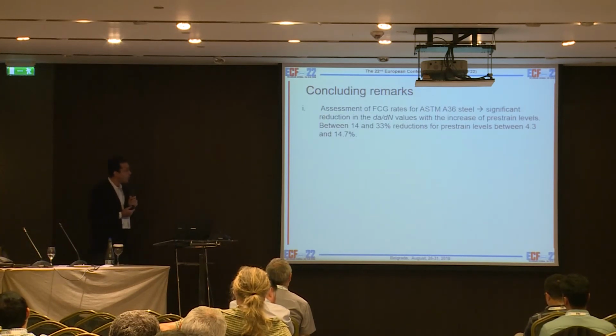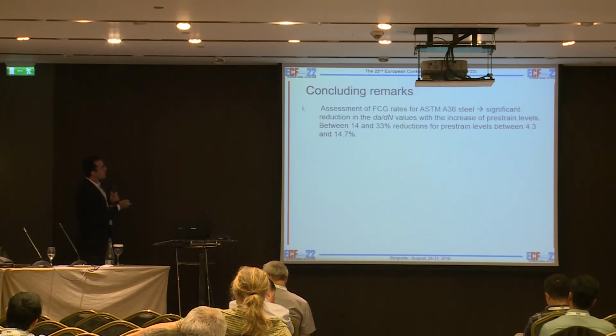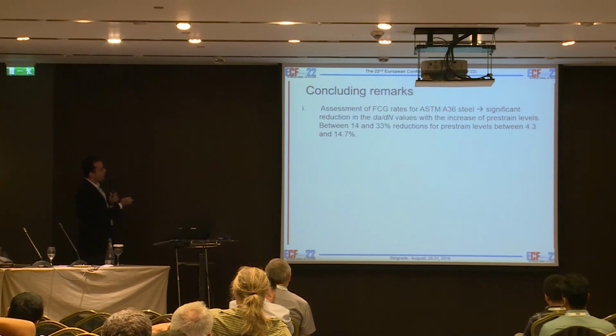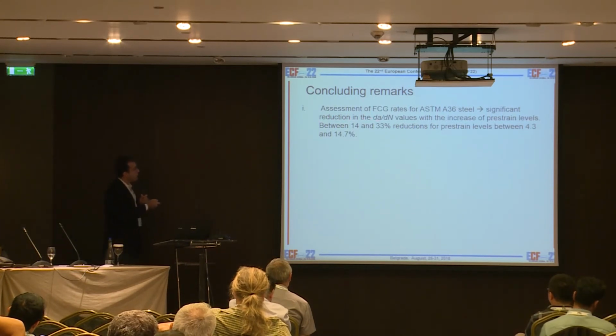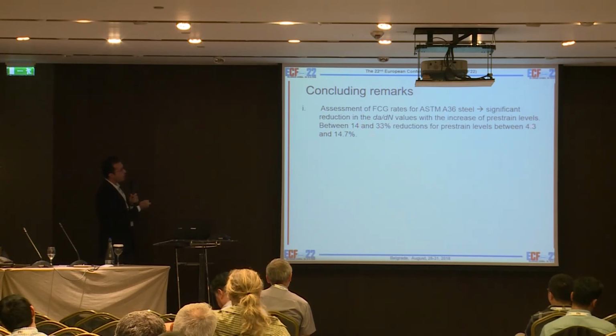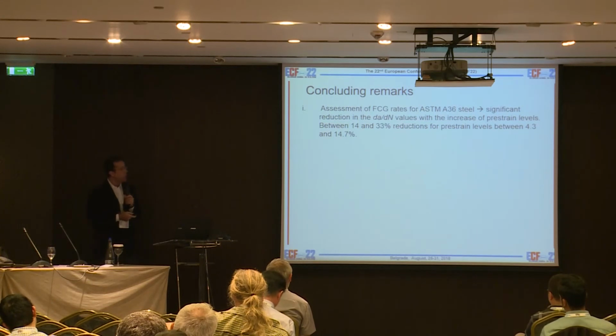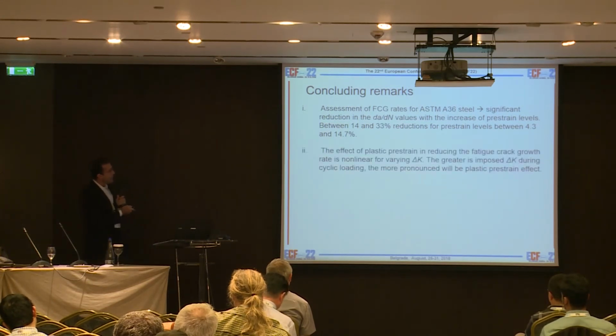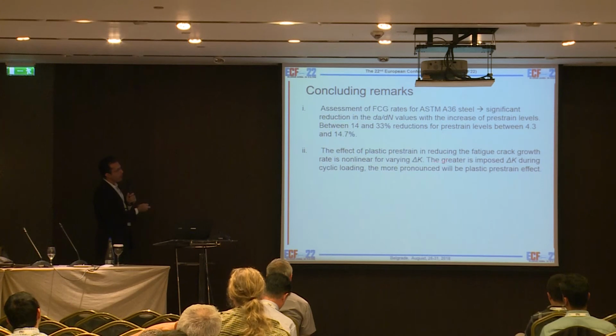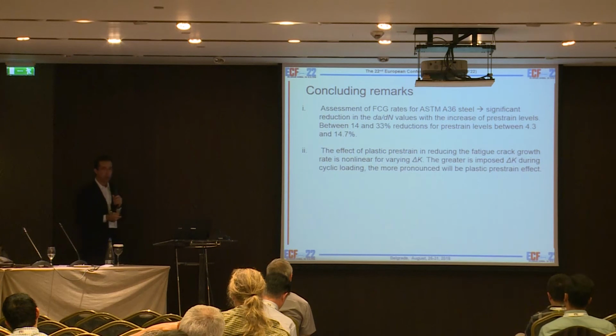So it's a suggestion. Concluding remarks: we could assess fatigue crack growth for the ASTM A36. We had a significant reduction in crack growth rates ranging from 14 to 33% if we consider 4.3 to 14.7% of plastic prestrain. The effects are non-linear with varying ΔK. So the greater the ΔK, the more pronounced the effect of plastic prestrain.